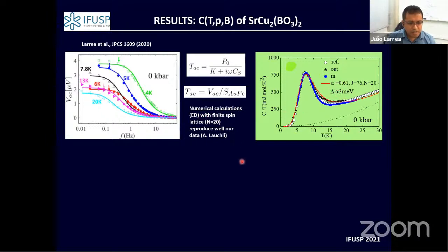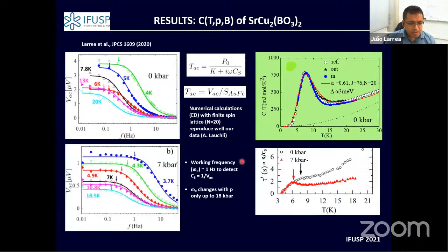Something interesting is that when we apply pressure, the frequency where the specific heat maximizes changes. Here I'm plotting the time relaxation, which is somehow inverse proportional to this frequency where you obtain the specific heat. You can see that this frequency changes with pressure.